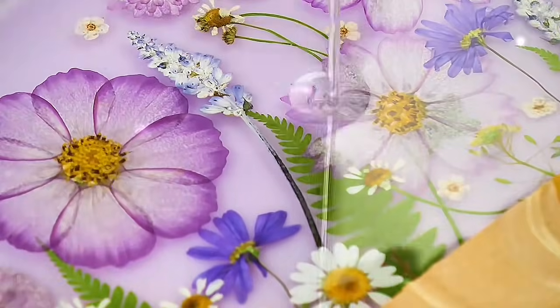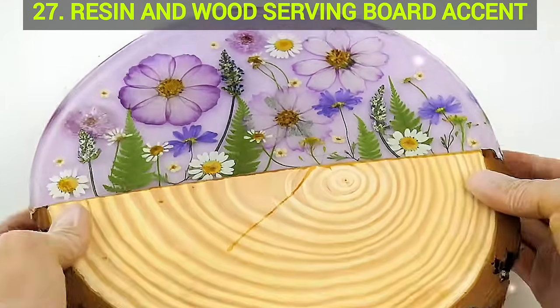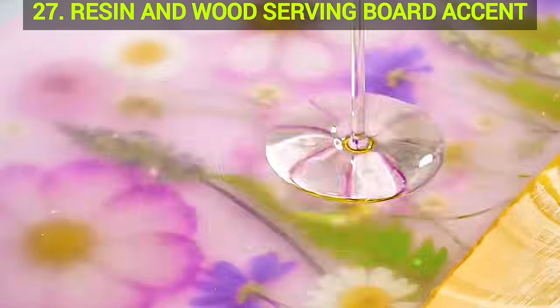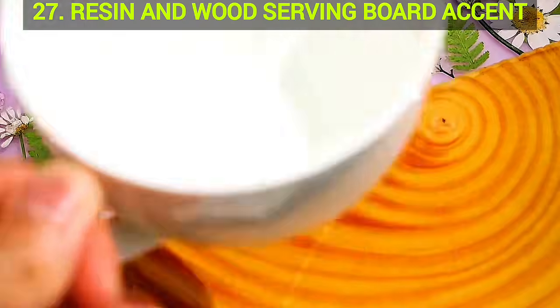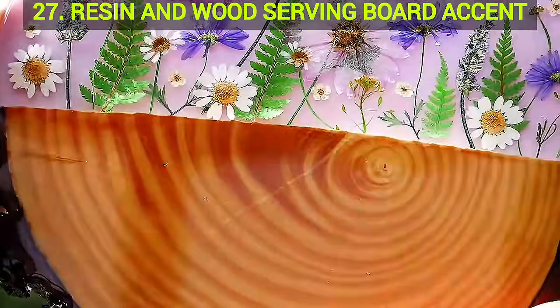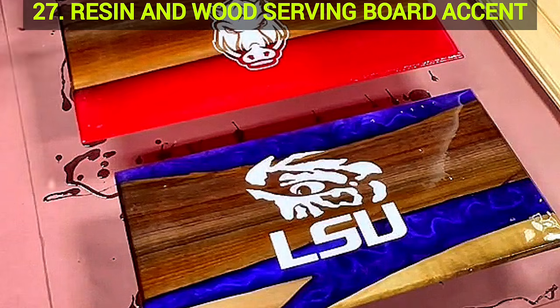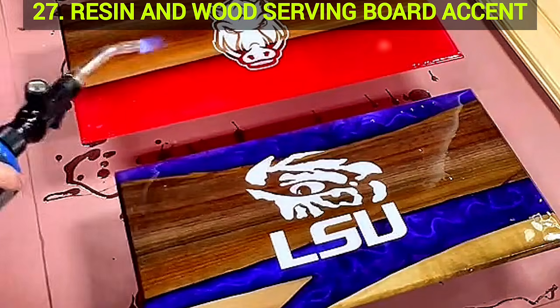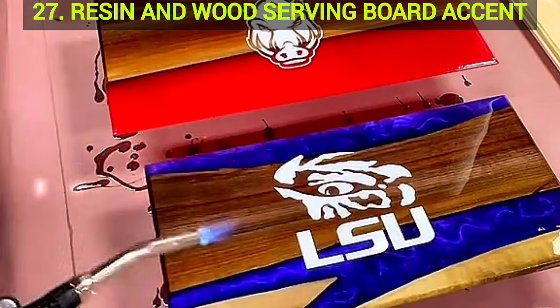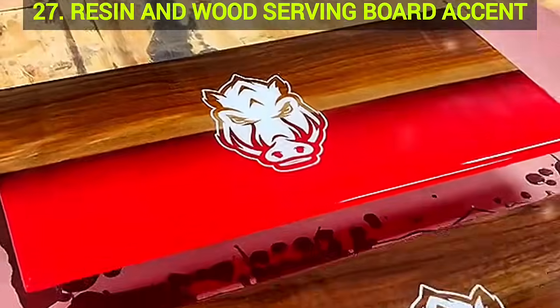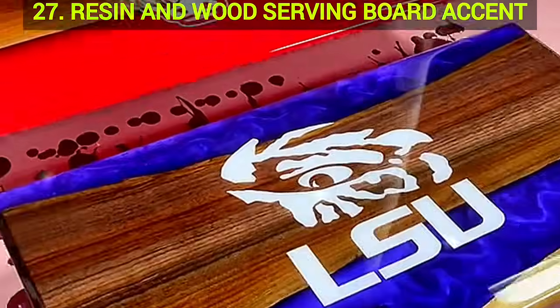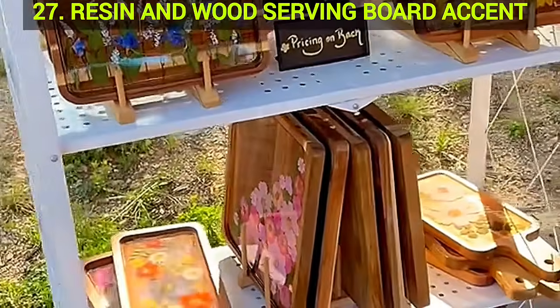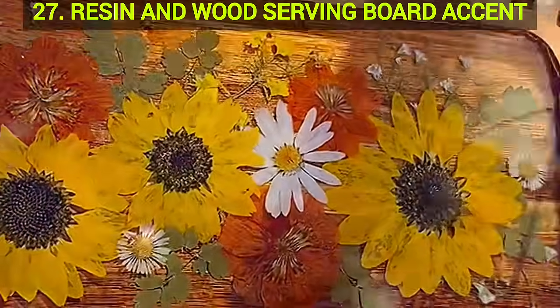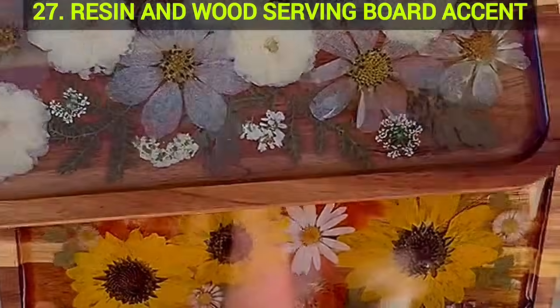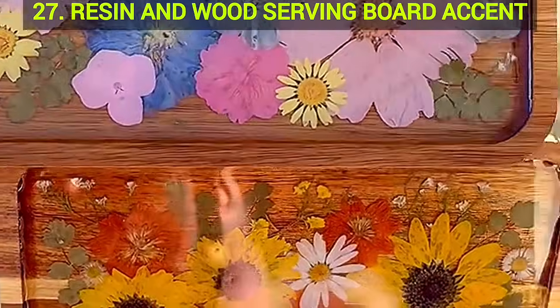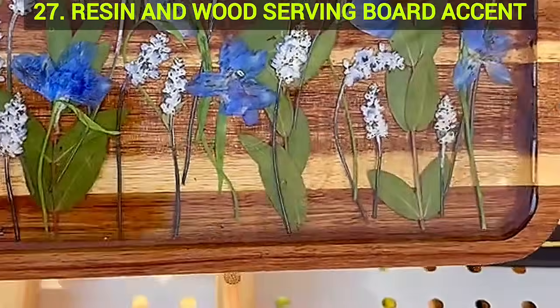Number 27, resin and wood serving board accent. A small oval resin insert poured into a routed channel in a wooden serving board creates the resin and wood combination aesthetic without requiring the full river table construction that large-scale resin wood projects demand. The oval channel is routed or carved into the wood first, the wood is sealed with tape, and a colored resin pour fills the channel. Sanding the resin insert flush with the wood surface after curing, using 400 through 2000 grit wet and dry paper, produces the seamless finish that distinguishes a professional result.